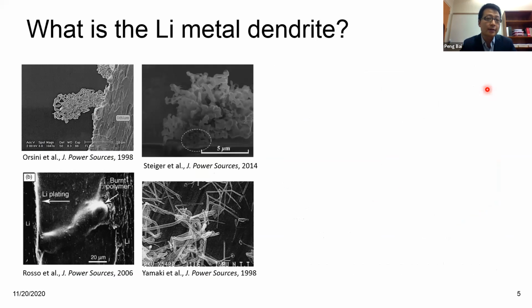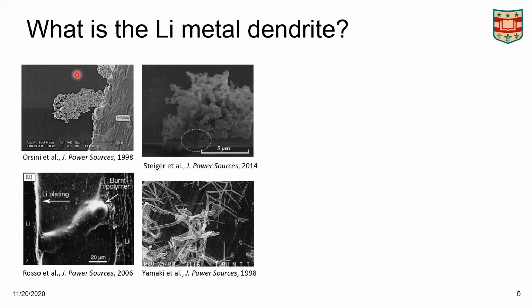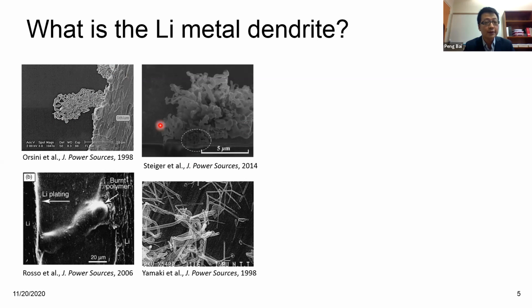So first of all, what is the lithium metal dendrite? For those who haven't handled or studied this subject, there are several SEM images. You can see here we have different forms of fibrous structure. Basically, you have long, thin fibers that are called dendrites. Even for this polymer electrolyte, you see this worm-like structure, which is actually not very thick. It's only about 20 micron in diameter.